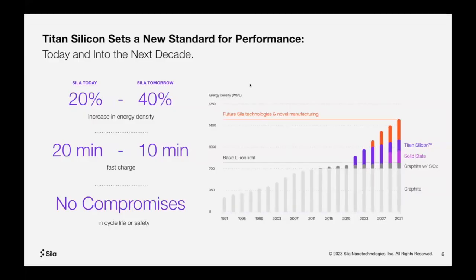In terms of performance of our material, so today I mentioned we get a 20% increase in energy density. By the end of the decade, we expect to be achieving about a 40% increase in energy density. So you can see here on the right, a chart showing what cells can achieve with graphite. They're basically kind of leveling out in their energy density. And then a comparison with graphite with SiOX, that's what Tesla uses now with cells from Panasonic. I show here what solid state can eventually achieve, and then showing what you can achieve with Titan Silicon material. And then the orange part there is what can be attained by other means combined with the silicon material, for example, improved cathodes. And you can see here the increase in energy density that can be achieved with all that combined together. So that's on the energy density side.